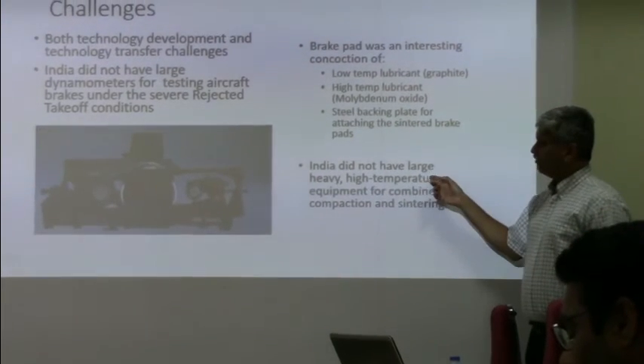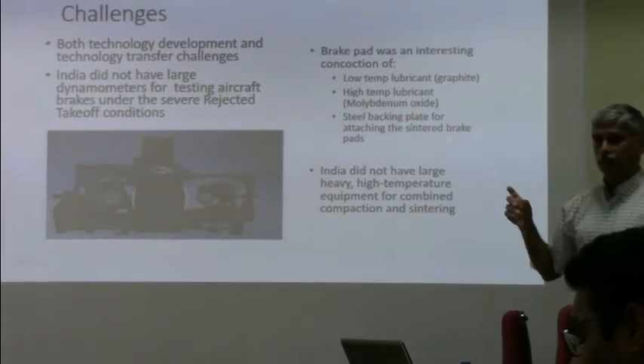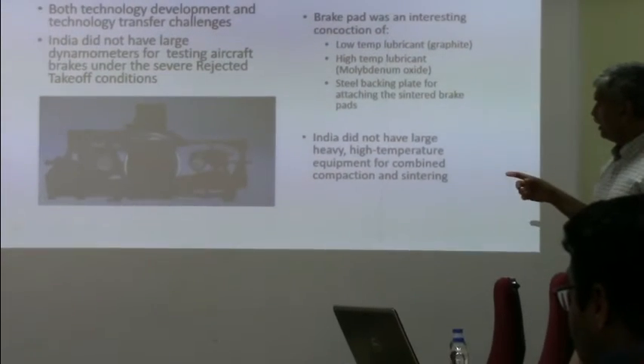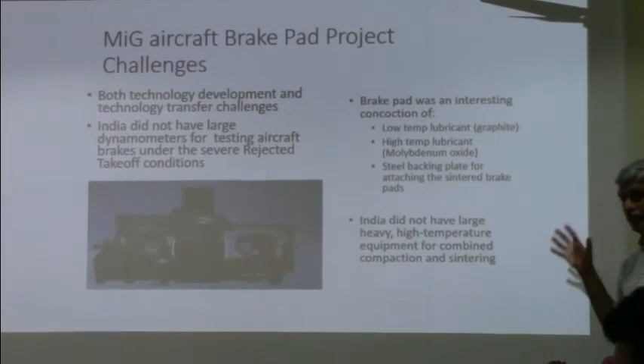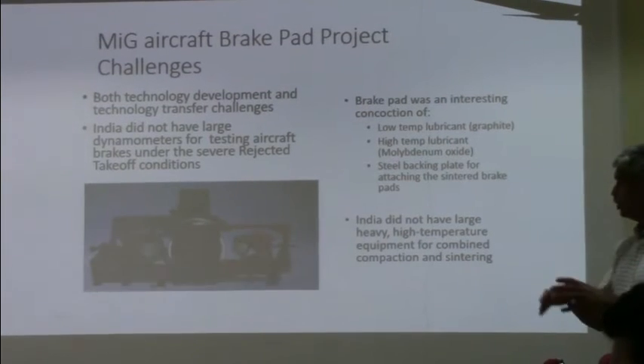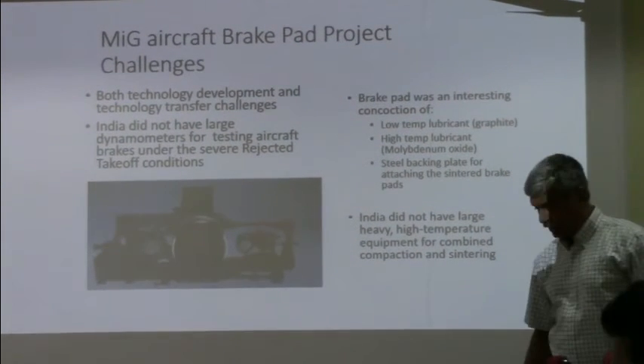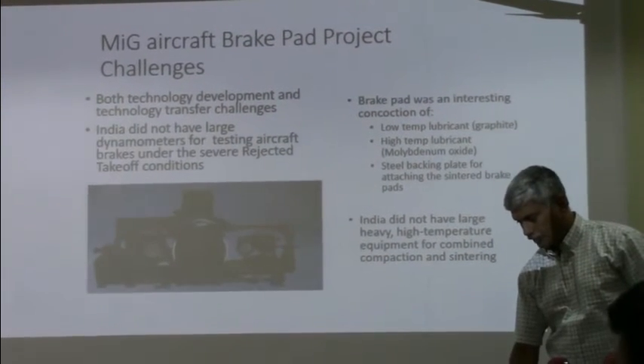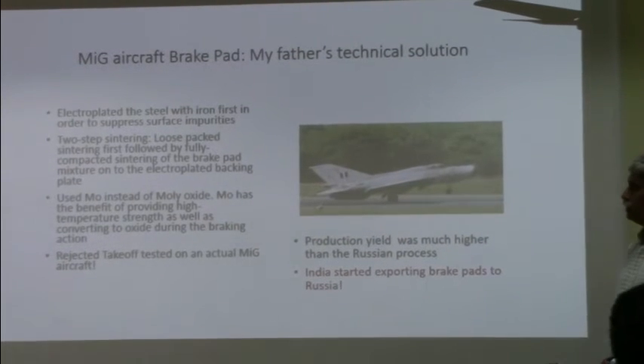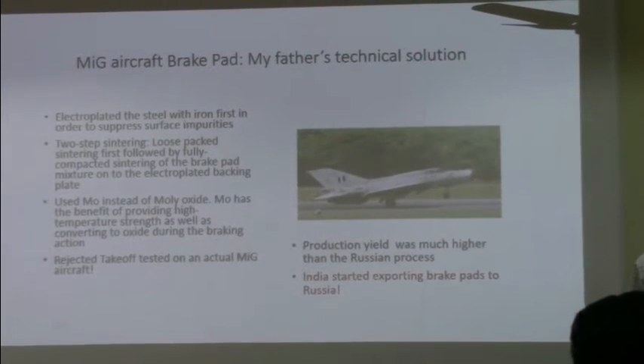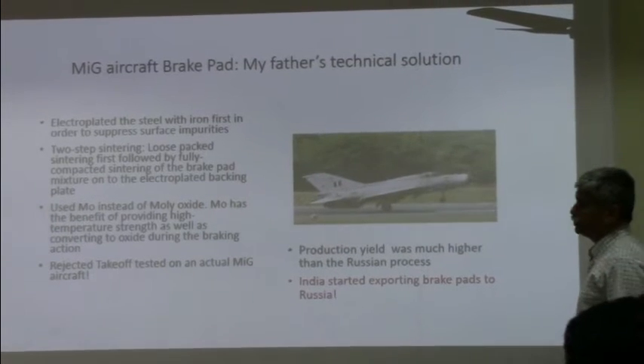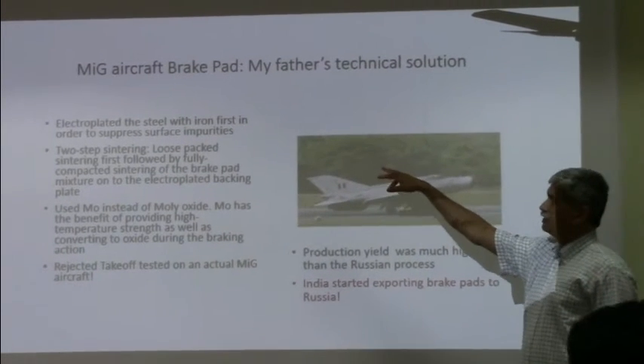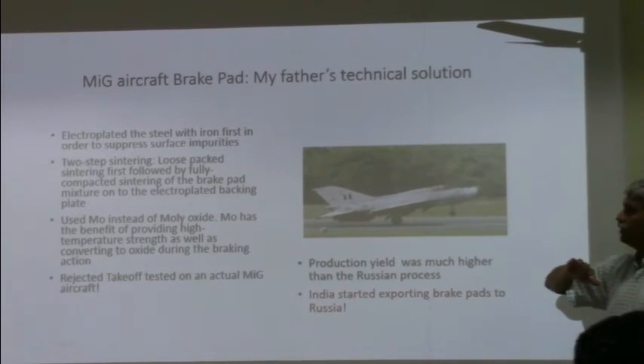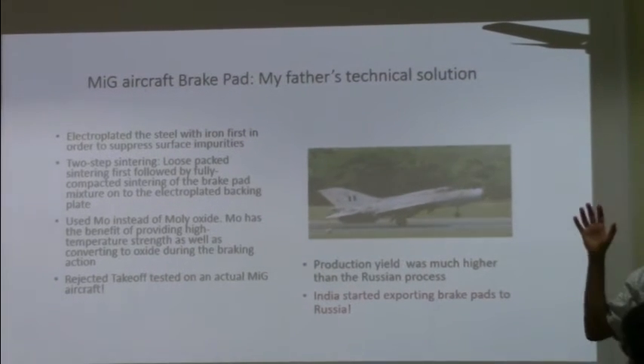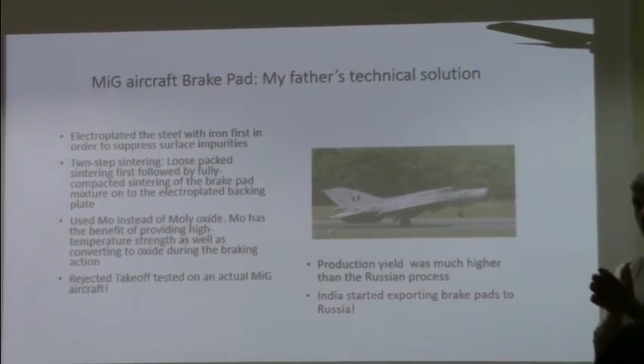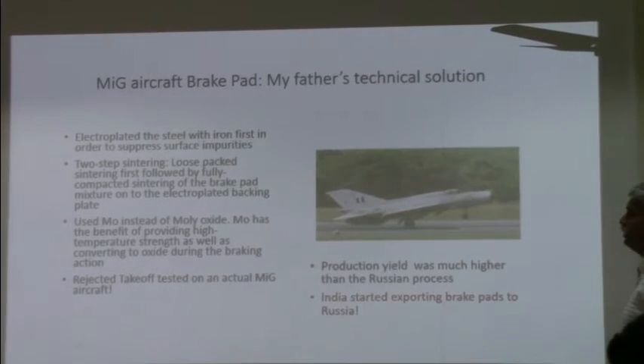So again, we did not have large, heavy equipment, high temperature compaction and sintering equipment for making this concoction onto a steel backing plate. So there were a number of innovations that my father came up with. The first thing he did was to electroplate this iron first in order to remove all of the surface impurities, because otherwise the sintered mass would not bond to the plate.